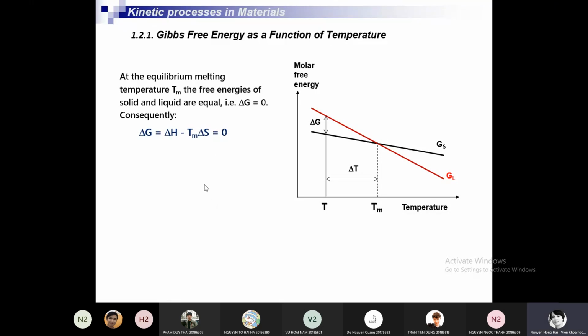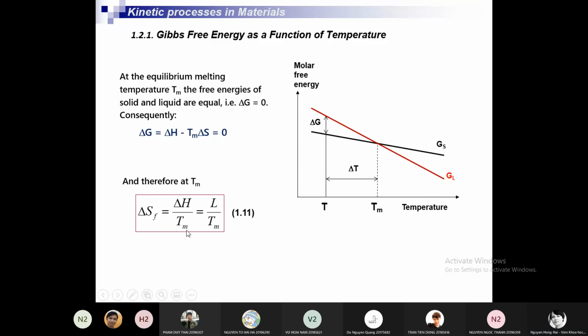Okay. So from this, you can find that delta S, the entropy of fusion, the entropy at this temperature, is equal to delta H over Tm. So delta H is the latent heat. So delta S_f is equal to L over Tm.